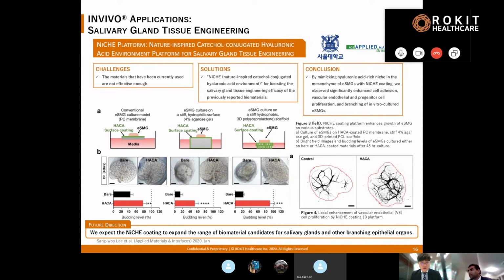So what they have compared here is conventional PC membranes, which I believe in this case is shown in the figures here. The group basically compared the conventional PC membrane, agarose as a key member of the hydrogels, and 3D printed PCL scaffolds as a representative of hydrophobic polymers. So the result showed that regardless of the surface, there was a very high amount of salivary tissue budding happening compared to the bare uncoated.